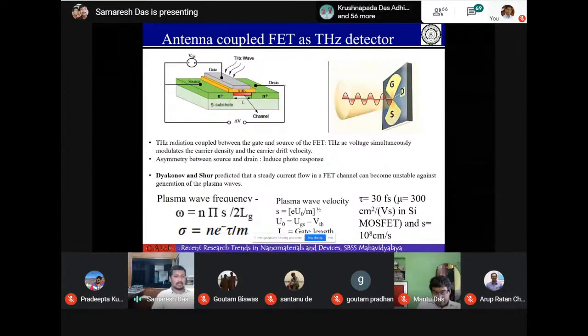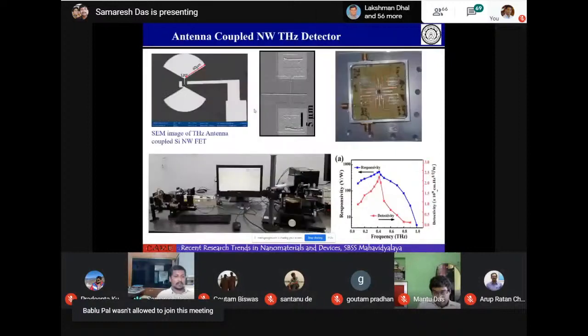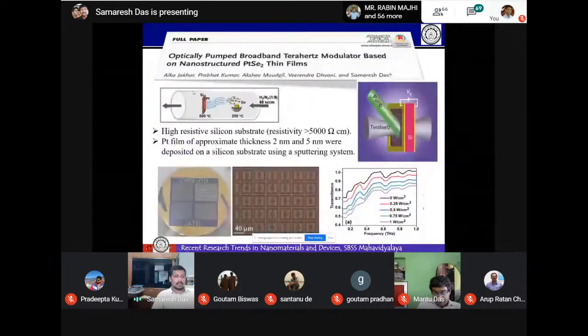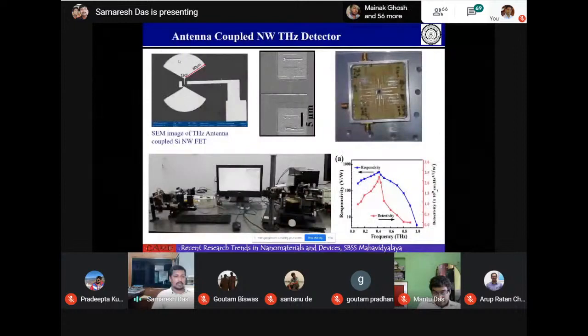But the channel length, like the gate length of the device, has to be smaller to get more coupling of the terahertz radiation to the channel. So we work to couple the terahertz radiation into the gate. This is the source, and this is the drain, and this is the gate. To couple the terahertz, we have to fabricate an antenna. This is the bow tie antenna we fabricate on chip, and the terahertz is absorbed by this antenna and coupled to your HEMT, and then you can get the source drain bias. This is a larger image of this HEMT, with the source, drain and gate. Then we make the device, wire bond and package it, because this is high frequency. Then we do the measurement, and we can see this is 100 gigahertz to 1000 gigahertz.